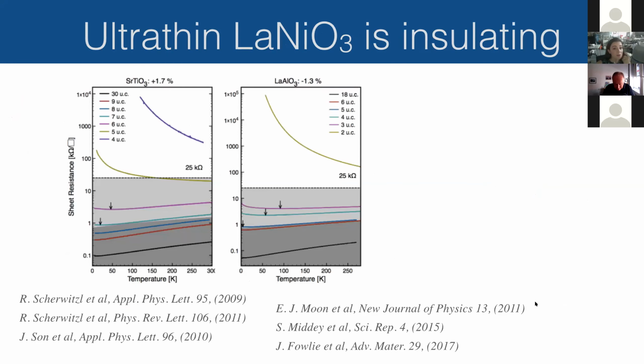Now, the next thing that I mentioned was that ultra-thin lanthanum nickelate is insulating. This is something that has been studied quite a bit already. There is a metal-insulator transition if you make lanthanum nickelate very thin, and you see that under 4 unit cells, you have insulating behavior. This is for 2 different substrates. The exact threshold under which you have insulating behavior depends a bit on the substrate. But still, it doesn't matter. Everything will become insulating if you make it thin enough. This is something that is kind of general to perovskite oxides, with maybe a few exceptions.